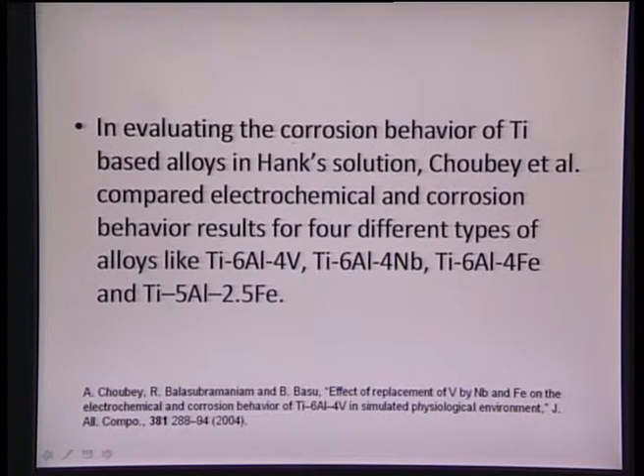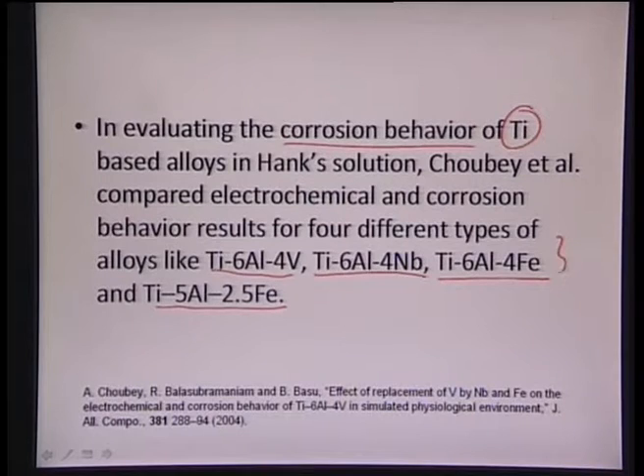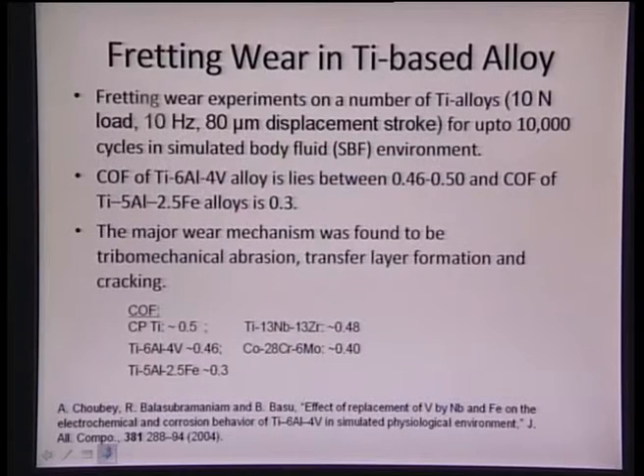There is one more group, Choubey, which has studied the corrosion behavior of titanium based alloys. So they have taken a couple of alloys such as titanium 6 aluminum 4 vanadium, titanium 6 aluminum 4 niobium, titanium 6 aluminum 4 Fe, titanium 5 aluminum 2.5 Fe. So they have taken 4 different types of alloys, and they have basically found their behavior in the Hanks solution. Then they have compared the electrochemical and corrosion behavior of all these alloys for different conditions. So that's what they have found out.